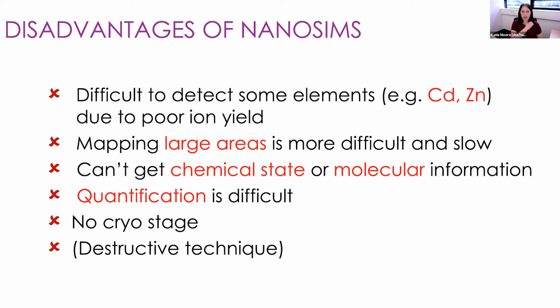We do not have a cryo stage on the NanoSIMS, and this can be an issue for lots of different application areas. Biology is a notable one. It means you have to go through some quite complicated sample preparation to get your sample into the ultra-high vacuum on the NanoSIMS. But specifically for this talk, hydrogen is a very mobile element, and a lot of our concerns when we started looking at these samples was, would we be able to find any hydrogen nanomaterials because we cannot keep our sample frozen and immobilize that hydrogen.